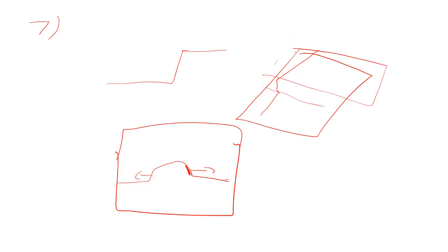Your penalty is the line tension to cause this, which is going to be related to the width of your dislocation core. Whereas if you're moving a big chunk of the dislocation, you're moving this whole region, but you don't have the penalty to pay for the curvature, for the line tension.